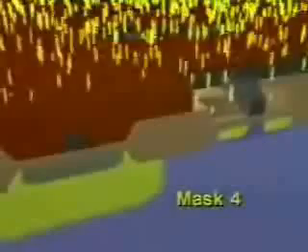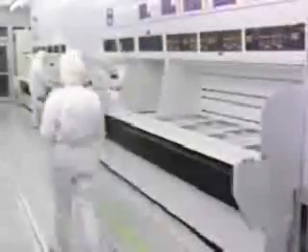Mask number 4 allows the implantation of the N-channel regions with a high concentration of N-type dopants to form the highly conductive source and drain regions of the N-channel transistors. Mask number 5 uncovers regions in the P-channel transistor, which are implanted with a high concentration of boron, a P-type dopant, to create the source and drain regions of the transistor. The photoresist is stripped, and again, the wafers are cleaned.